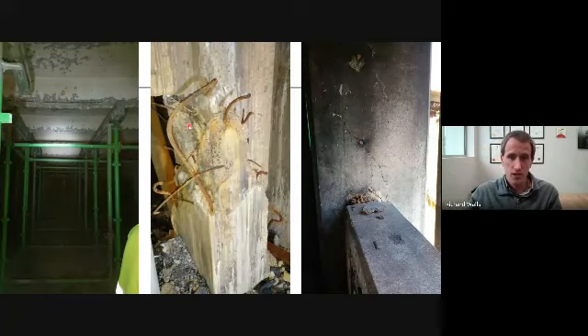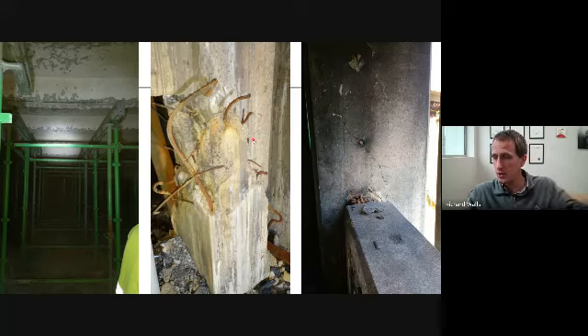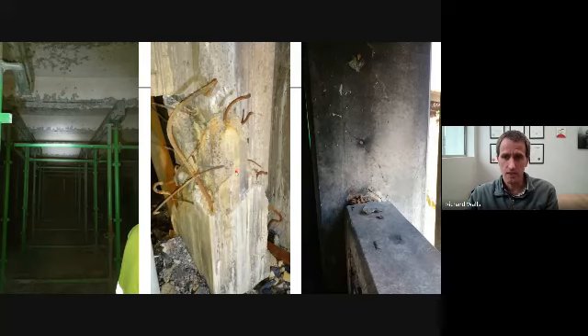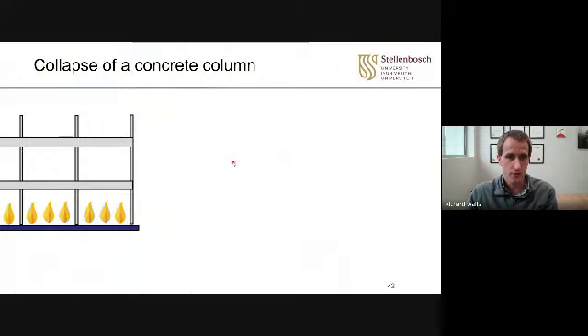What even happened in the structure, there's major structural collapse, there's spalling. This is a column. Now, this is a big column. This is a 600 mil by 600 mil column. This is a big chunky thing supporting, I think it was about 500 tons, if I stand to be corrected, or maybe it was even 1,000 tons, can't remember offhand. And it's very heavily reinforced. But what happened is that the beam actually caused this entire thing to fail, and it cut it in half, and about a meter of column is missing. On a perimeter column, the beams actually pushed it out and caused major, major structural cracking through the elements. So collapse of a concrete column.